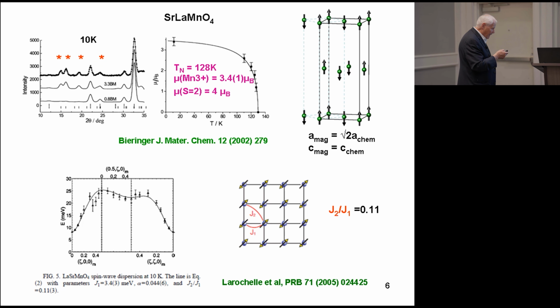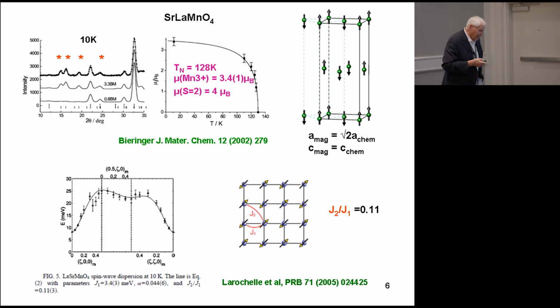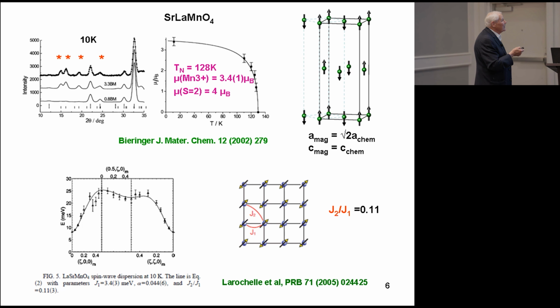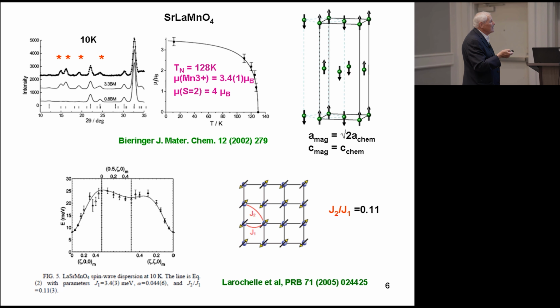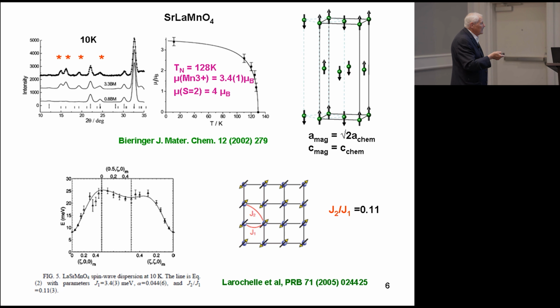Okay, so this is part of Mario's PhD work, and this is some of the last neutron diffraction data that we took at the McMaster reactor. And we started looking at this strontium lanthanum manganese Ruddlesden-Popper phase, and as it turns out, it's an antiferromagnet with a Néel temperature of 128 Kelvin. This is a magnetic structure, as you can work out. Other people have grown single crystals and worked out even the spin wave structures. This is a well-studied and well-known material.